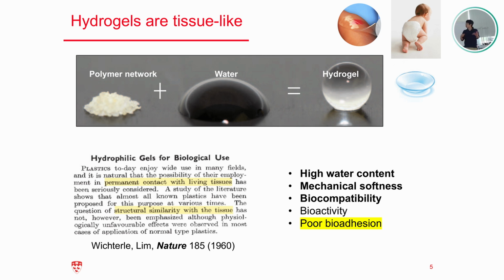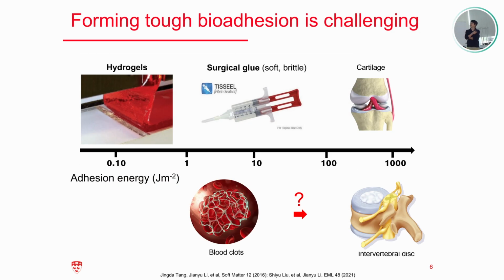So the most notable limitation, at least for me as trained as a mechanical engineer, is the poor bioadhesion property. That is not surprising. If you consider the hydrogel, again, those are aggregates of polymer and a large amount of water. The water molecules essentially serve as a solvent, and they do almost nothing, right, to enable the adhesion. Instead, they try to limit the binding between the polymer network and the substrate, right?